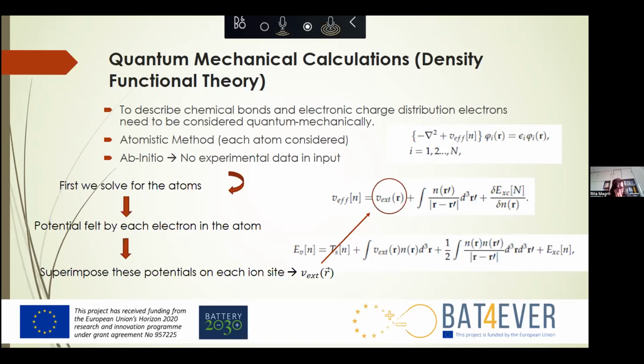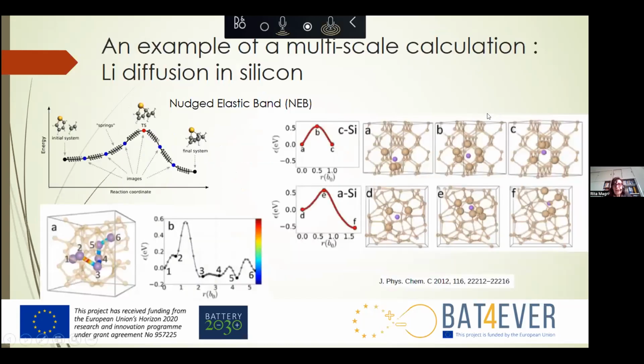Then when we have all these potentials felt by the electrons in that atom, we superimpose the potentials, centering each at each ionic site. And so we build an entire potential, which is called in this case the external potential, which is the effect of all the ionic cores on all the electrons. And once we have solved this self-consistent problem, we are able to calculate the total energy of the system. This is useful not only to calculate the intercalation energy and the open circuit voltages, but also to simulate, for example, lithium diffusion in silicon.